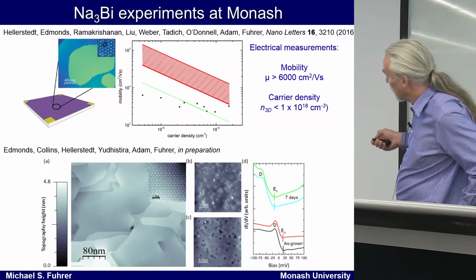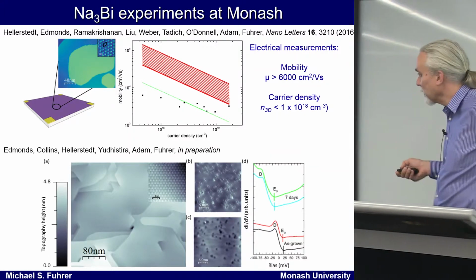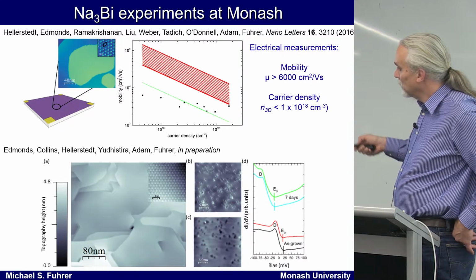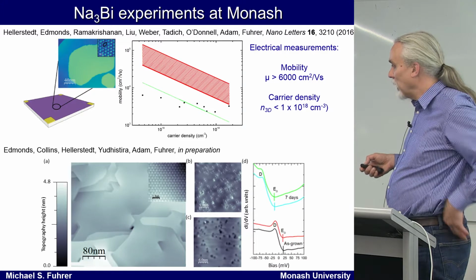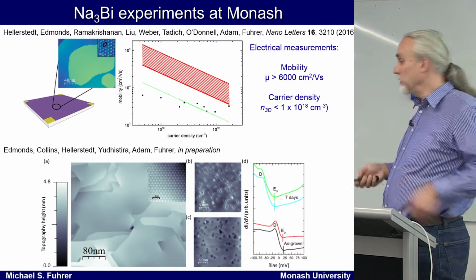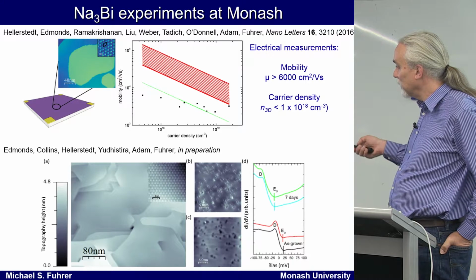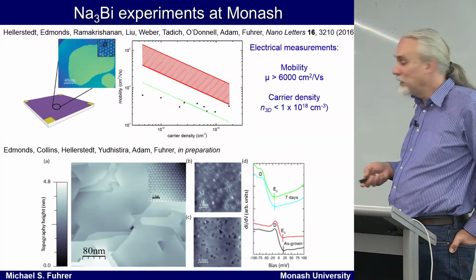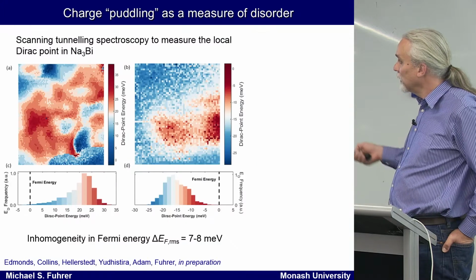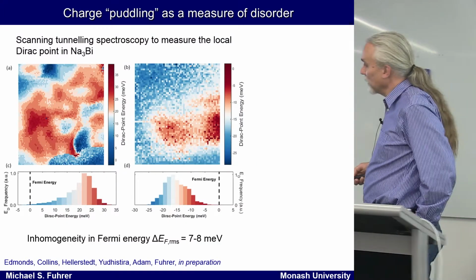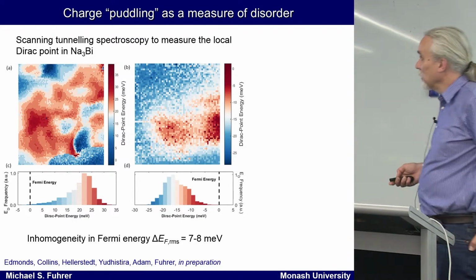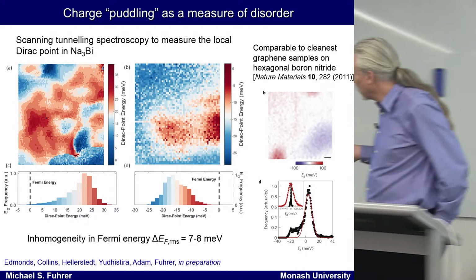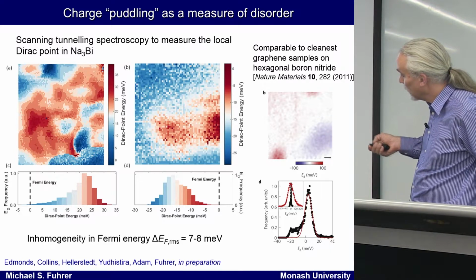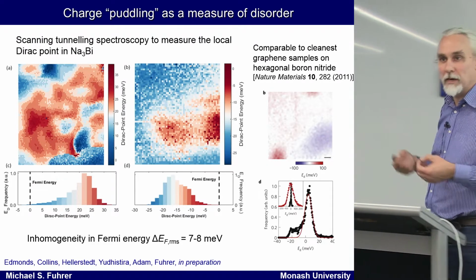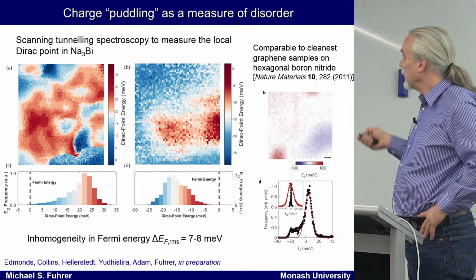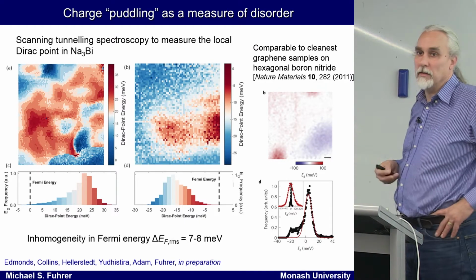This is a really fantastic sample that Mark and James have been able to grow that has really large terraces, and now they're mapping out the local Dirac point in this material with scanning tunneling spectroscopy. You can see this minimum, which corresponds to the Dirac point, and map out its spatial variation. And these are sort of maps of the spatial variation of the Dirac point. And the really nice thing is that we can get really close to the Dirac point in energy. So the Dirac point only varies by a few millivolts, 5 millivolts in space. And that's comparable actually to the very best graphene samples.